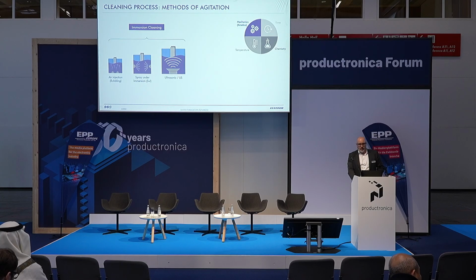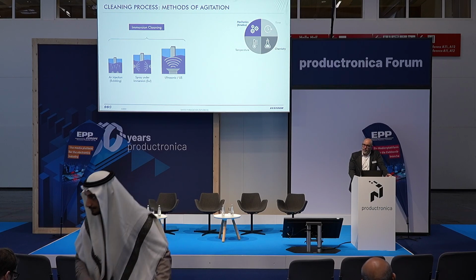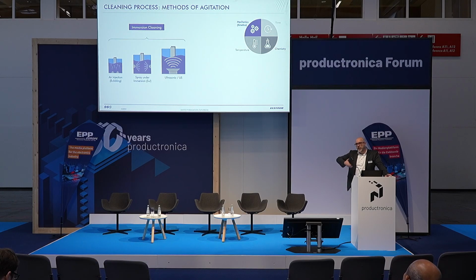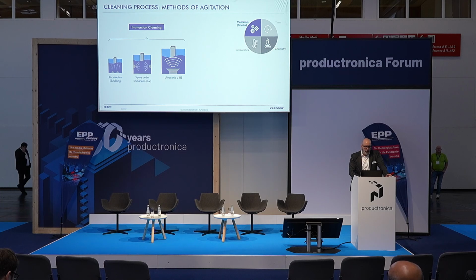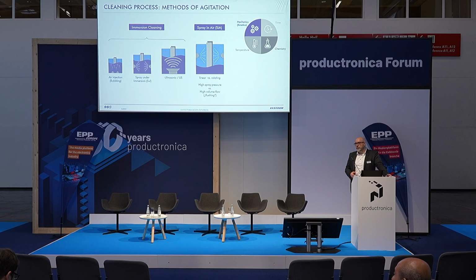Okay, so regarding mechanics in the Sinner's circle I just mentioned, there are different methods of agitation, which is the process of basically moving the cleaning and the rinsing fluid in the cleaning machine. So you have on the one side immersion cleaning, where you dip the PCBA, for instance, in the cleaning media, and then you have some agitation by either air bubbles or ultrasonic devices or spray under immersion. Or you have a so-called spray in air process, where the goods are basically still in air in a holder, and then you spray the medium onto them. So these are the 2, let's say, main differentiations.